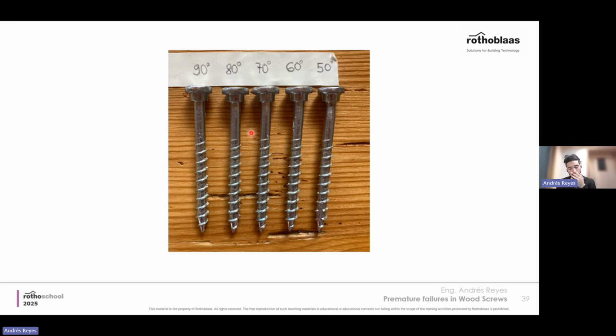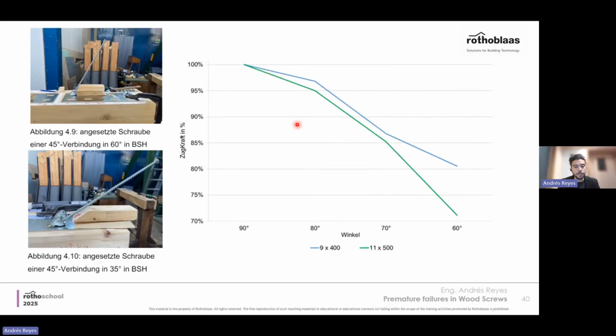When you screw them with an inclination angle, that means that there is an effect on the tensile capacity that we will see afterwards, but also definitely there could be some micro cracks in the structure of the screw and micro cracks in the coating that could lead to corrosion, and they would favor hydrogen-induced cracks and hydrogen-induced corrosion, hydrogen embrittlement. So to answer the question, how much can bending affect the tensile capacity of the screws, these are our results.